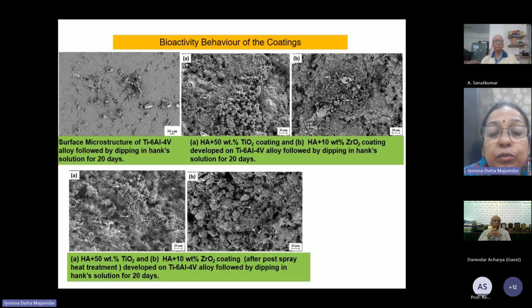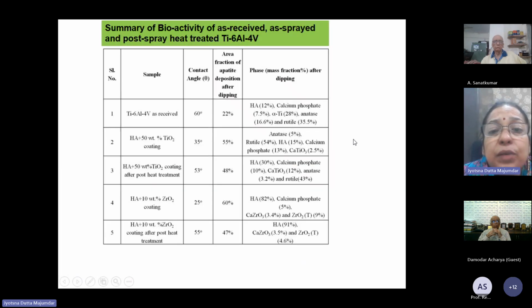By weight change measurement, after each hour of dipping, we found the rate of weight change as a function of original weight. Partly there is weight loss because of dissolution, and weight gain is because of deposition.